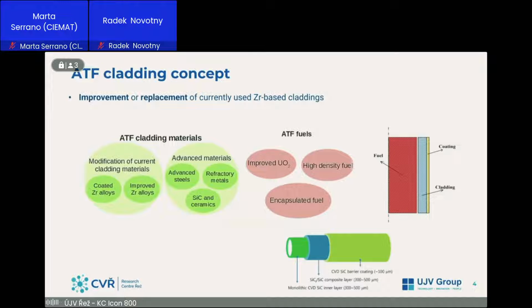Among the perspective materials, we can mention the chromium-coated zirconium alloys, which have been tested in nuclear power plants since 2019. As well, a very perspective material is the so-called FeCrAl, an iron, chromium, and aluminum-based metal, and widely tested are silicon carbide materials among the ATF cladding materials. For ATF fuels, there is the way to improve uranium oxide material to develop high density fuel and encapsulated fuel.